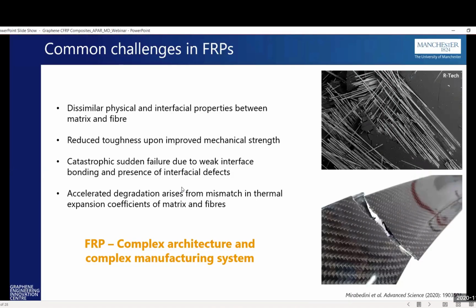So the first one being, what are the common challenges that exist in fiber reinforced plastics? So fiber and the matrix themselves are two different materials with completely dissimilar physical and interfacial properties. Because of these two different properties, they typically have a weak interface, and because of the weak interface, any defects that may be present in the interfacial area can lead to sudden and catastrophic failures. And because of this property difference, these two different materials have completely different thermal expansion coefficients, which could actually cause accelerated degradation as well. So it's fair to say that the FRP is a complex architecture in itself, and the production methods to produce these composites are quite complex because of the parameters that are being considered.